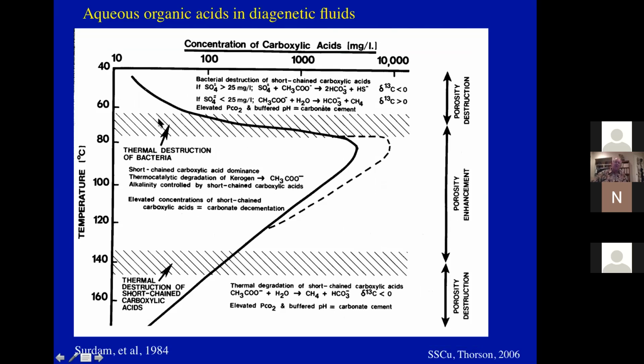And along with the generation of hydrocarbons out of unmatured organic material, there is a generation of a large amount of organic acids. These are organic acids that are chemically similar to vinegar, which is acetic acid. And on this diagram from Surdam's work at the University of Wyoming, this is increasing temperature, which essentially is increasing depth in a sedimentary section. At low temperatures, you have some organic acids generated. This is the concentration of these carboxylic acids, these acetic acid like organic acids.